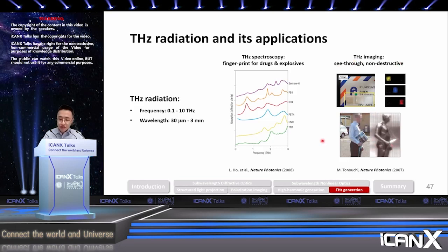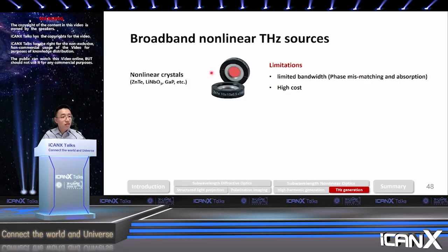One of the conventional ways to generate broadband terahertz is using a nonlinear crystal, such as zinc telluride. But it has the limitation of a very limited bandwidth, typically smaller than 3 terahertz. That is limited by the phase mismatch as well as the absorption of the nonlinear crystal. Also, these nonlinear crystals are not cheap, typically greater than $1,000 US.